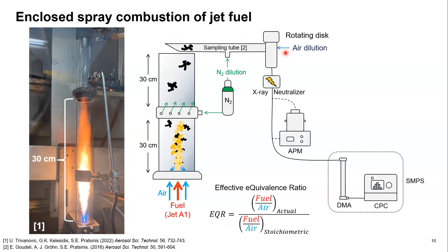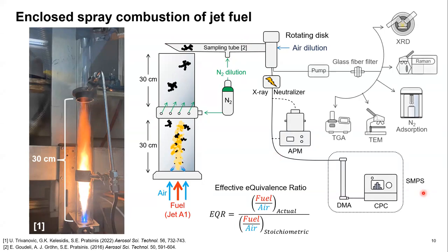This diluted fraction is sent to our online diagnostics, in this case, the aerosol particle mass analyzer and the scanning mobility particle sizer. There's also a pump, which is sampling particles which bypass the rotating disk and are deposited onto a glass fiber filter for offline analysis. This offline analysis includes thermal gravimetric analysis, transmission electron microscopy, nitrogen adsorption, which we use to obtain the specific surface area, Raman spectroscopy, and X-ray diffraction.